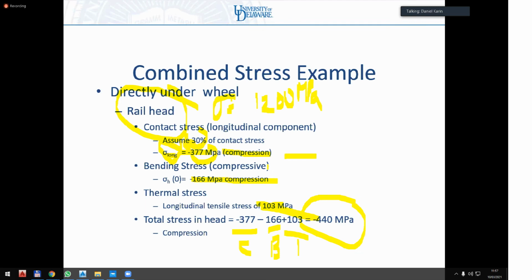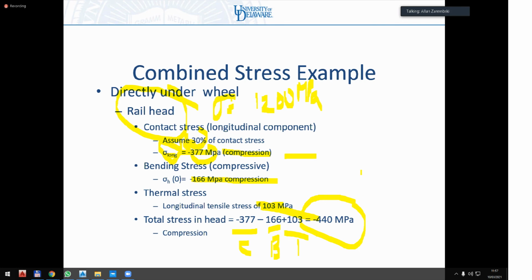And the thermal stress can be positive and can be negative. Absolutely. If the rail temperature is above the neutral temperature, then you're in compression. If the rail temperature is below the neutral temperature, then you're in tension. And you can be 50 degrees above, you can be 50 degrees below. Even though the way most people do it, you're usually going to be lower, so you're going to have more tension.